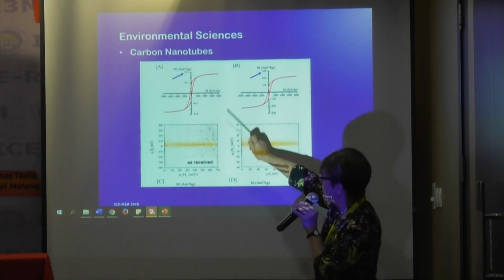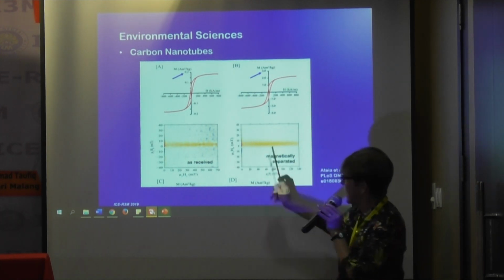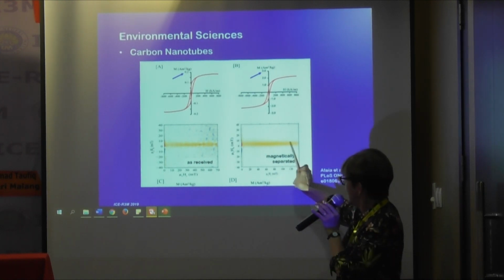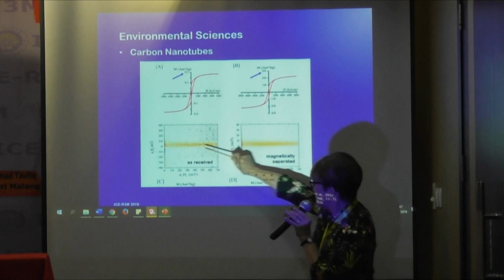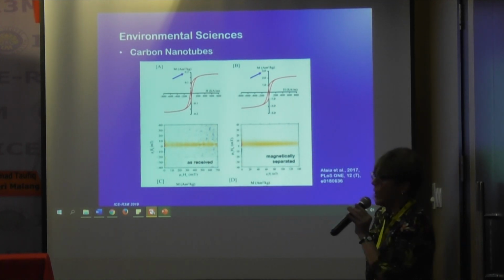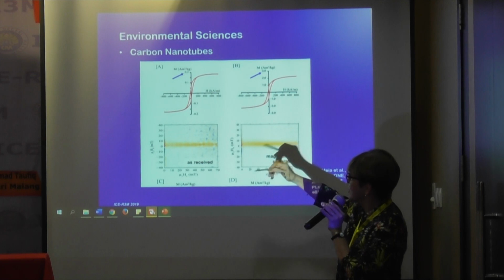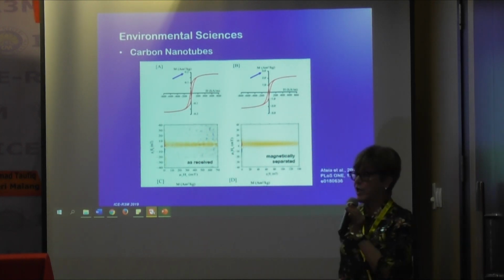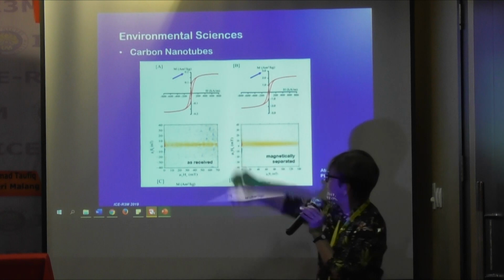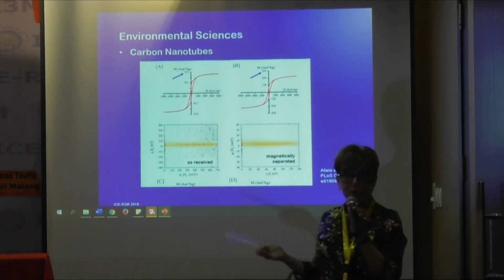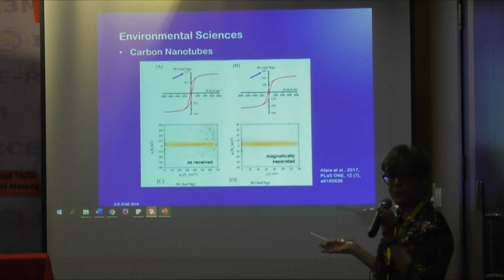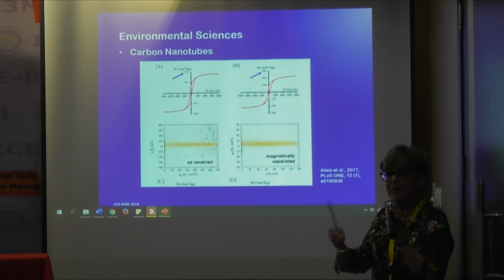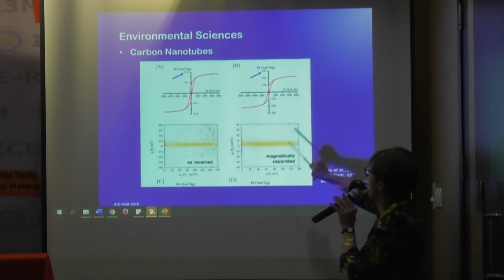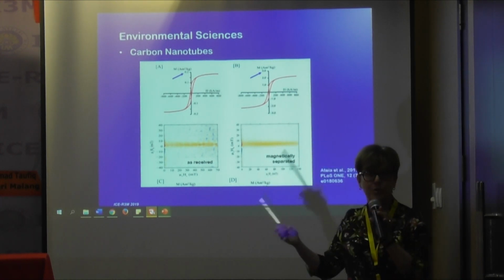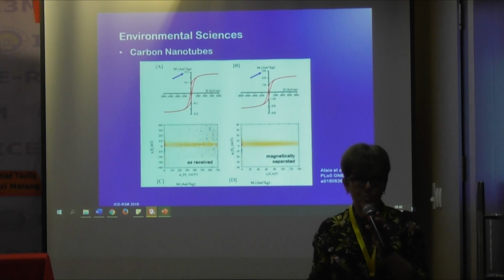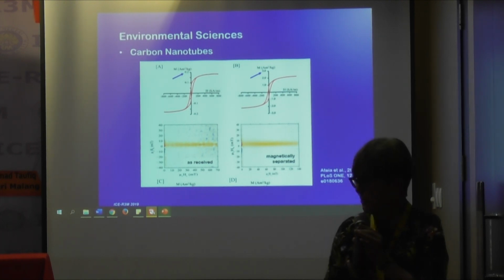So we measured hysteresis and FORC diagrams. You can see the FORC diagrams look the same for both. You have something here that's blocked, and you have something here, again, the superparamagnetic part. What you do see, though, is without separating out the strong magnetic material, the material in general has a saturation magnetization on the order of 0.2 ampere meters squared per kilogram. But if they pick out the more magnetic ones, they go up by a factor of 10. So we're up at around 2.5 ampere meters squared per kilogram. So they found that worked very well.